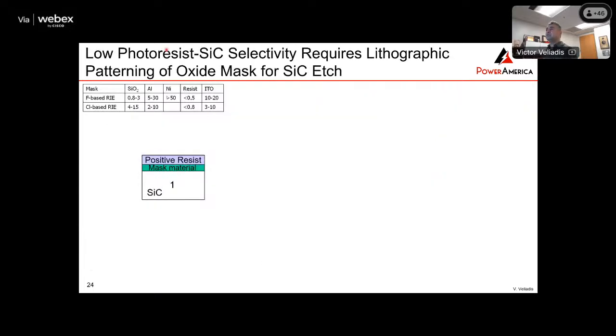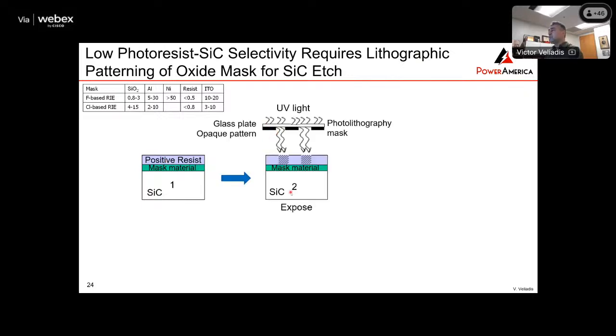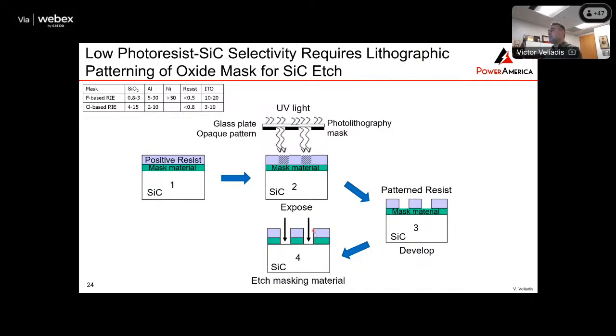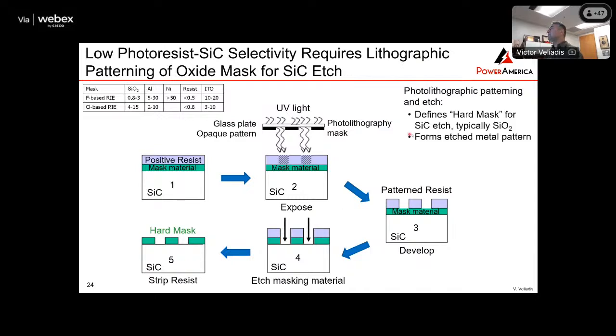Let's look at the process now to do the etch. You deposit the mask material, whether that's an oxide or a metal mask, and then you put the resist. The next step is to go to the lithography equipment and expose the resist and then develop it. So the areas that got exposed, if the resist is positive, these areas dissolve away, and now you've got your patterned resist and the mask material, which typically is an oxide. You etch away the masking material, okay, and now you're at the silicon carbide surface, and you get rid of the resist, and it's really this hard mask that's going to be used to etch down in the areas that are open to do the etch.